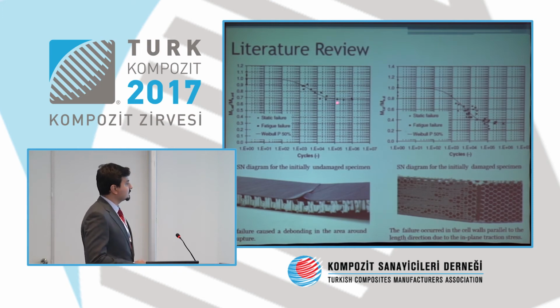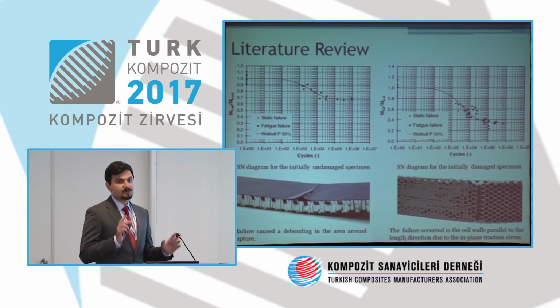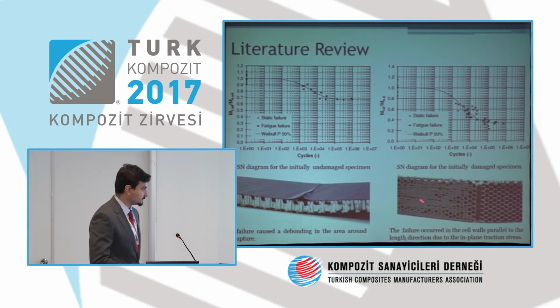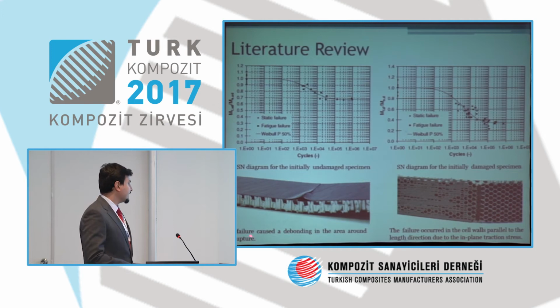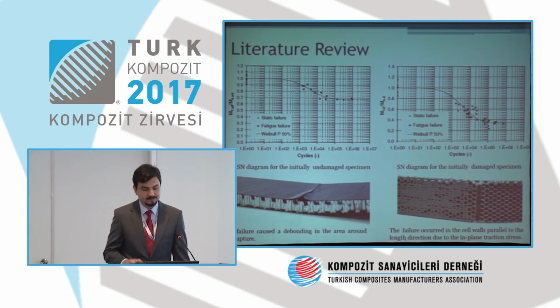And their results for undamaged specimen and also the damaged specimen. This is the important one, the failure modes. They indicated that the failure caused the debonding in the area around the rupture, this one, for undamaged specimen. And the failure occurred in the cell walls parallel to the length direction due to in-plane traction stresses, you can see here, for damaged specimen.